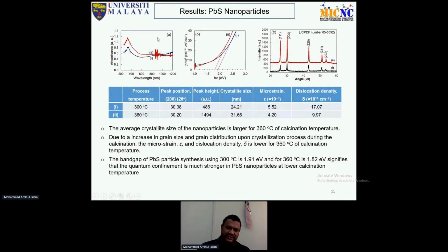You see the UV-Vis results, which is the absorption for the nanoparticles at 2 temperatures. That means one is 300 degrees centigrade and 2 is 360 degrees centigrade. When we calculate the band gap for these 2, we got 1.91 and 1.82. So the band gap is higher for the 300 degrees centigrade. This is the crystallographic structure, and in comparison we see 360 degrees giving the higher crystallinity. We also calculate the crystal size, microstrain and dislocation density. We see the crystal size is also higher for 360 centigrade.